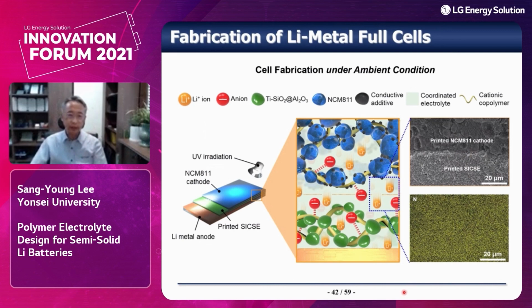Here, the important point is that this cell was fabricated under ambient conditions. No high temperature and no high pressure were needed to fabricate this cell. Just printing followed by UV curing is enough.